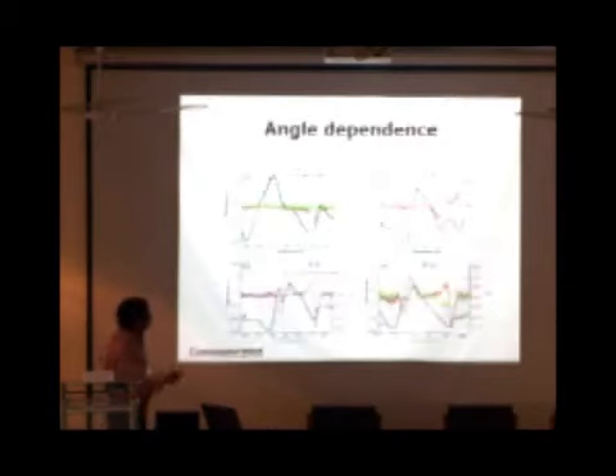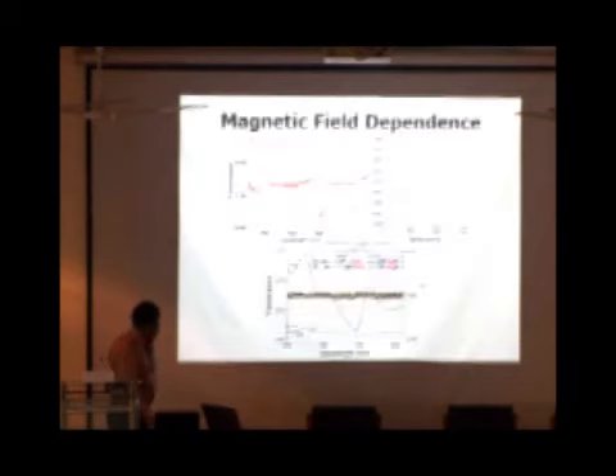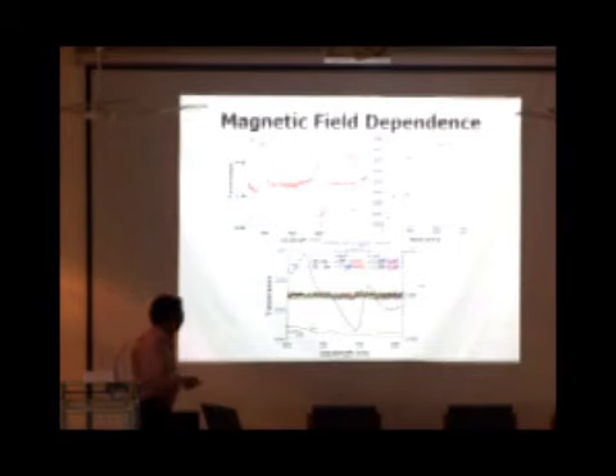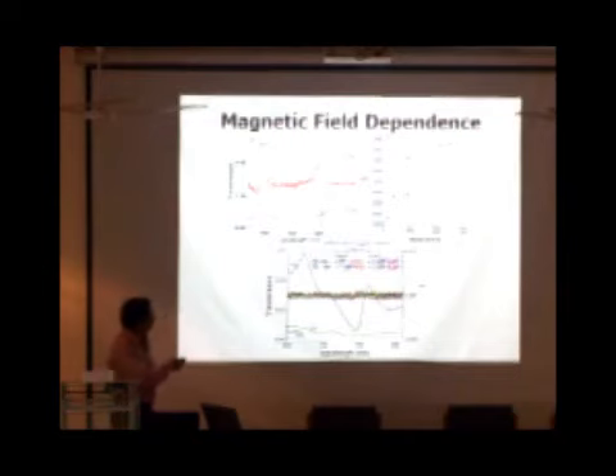So we've done the angle dependence under different orientations. This has been communicated, along with the magnetic field dependence. As I said, you can choose the orientation of your magnetic field and the polarization of your light, to get both surface plasmon and MOKE in one case, or only the Kerr effect, or nothing at all, or only surface plasmon excitation. So you see that the enhancement is seen only when you have both present.